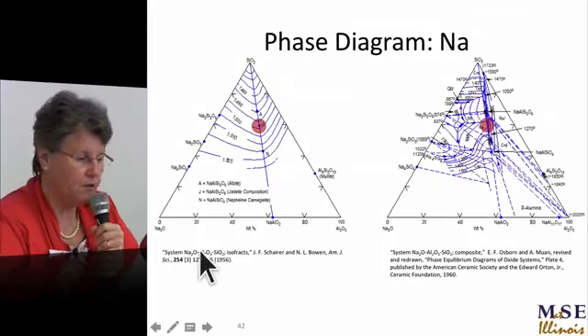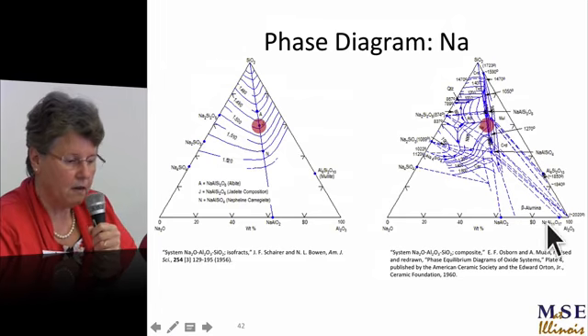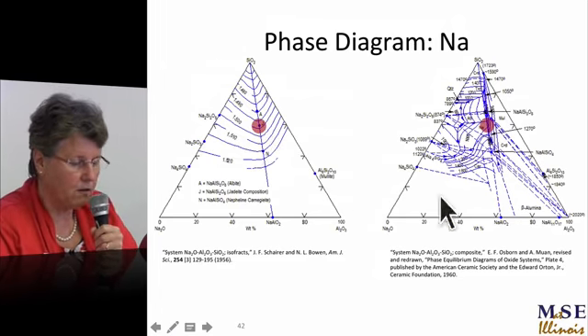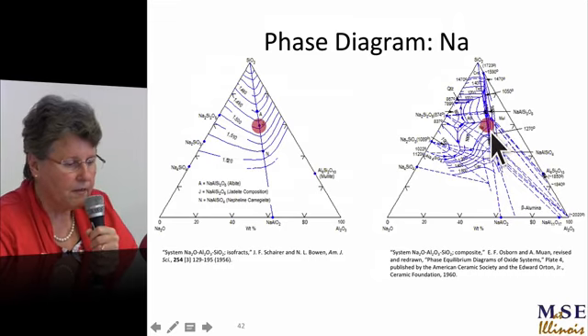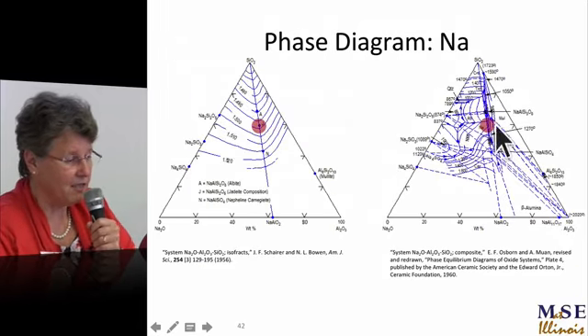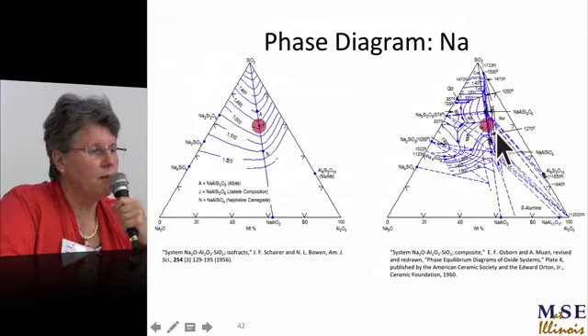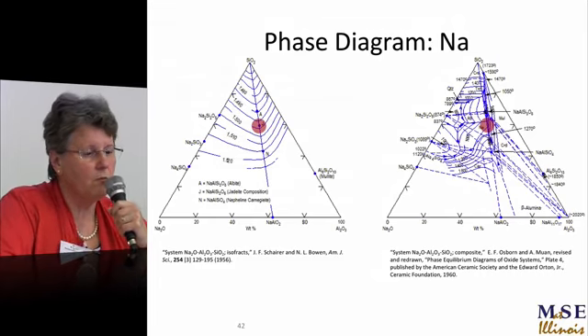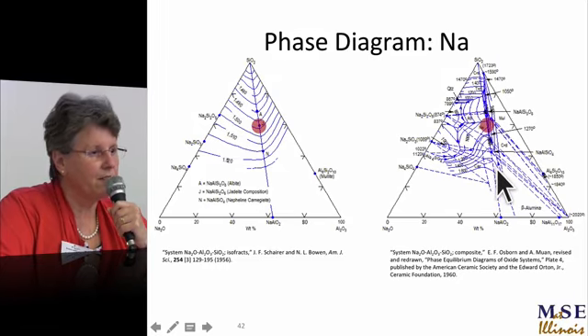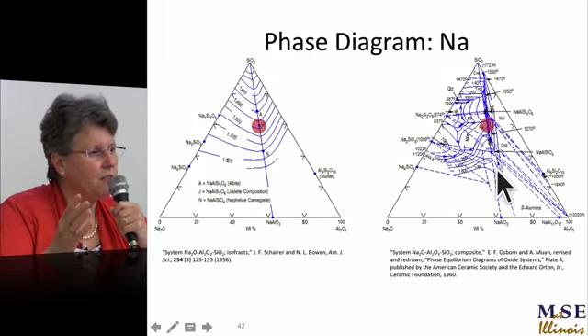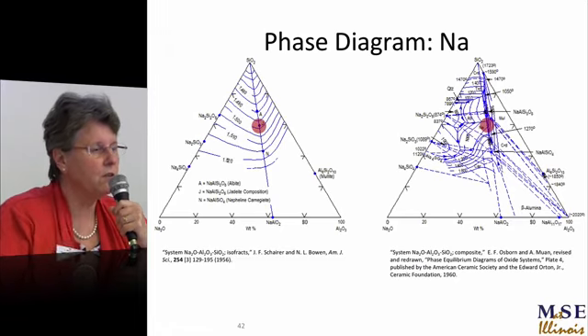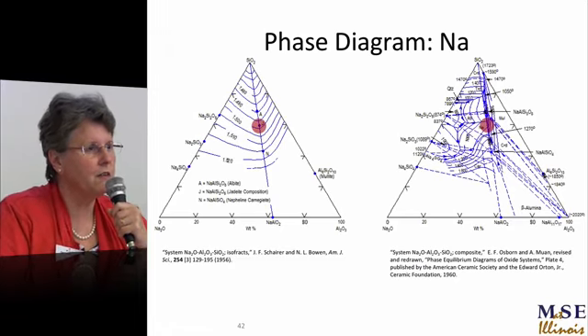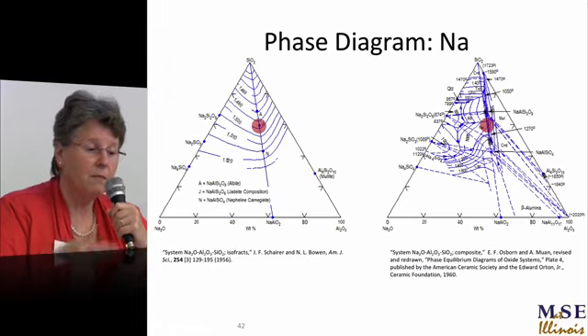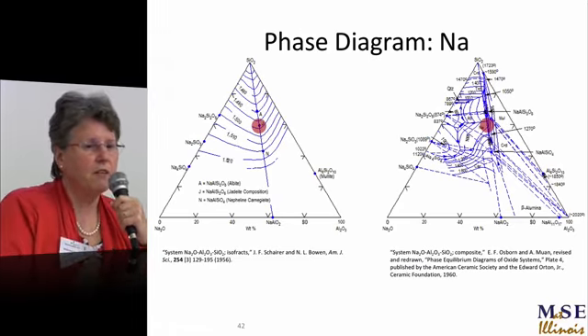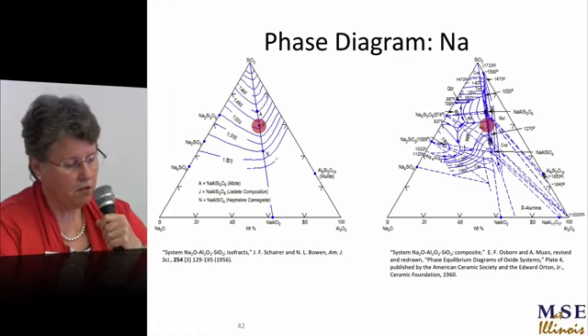There's a phase diagram: sodium aluminosilicate, and the 1,1,4, that's weight percent, this is mole percent, I think. The 114 compound is here. That's the geopolymer composition. But to make sodium into a ceramic, you don't get 114, you get 112. That's called nepheline. 114 is jade, the toughest mineral. But you need geological pressures, 1.7 gigapascals, 1250 C to make jade. That's a synthetic way to make jade, if you've got some friends in the geology department.